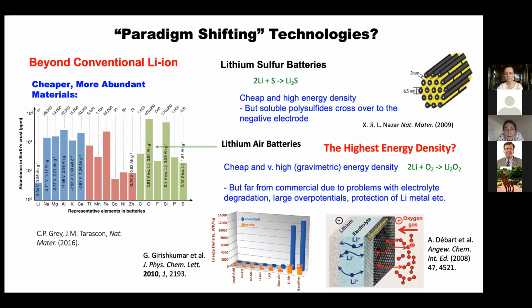If you really want to go cheaper, you should get rid of your transition metals, and maybe you can use sulfur and make a lithium sulfur battery, and you get very high energy densities because both lithium and sulfur are light, and of course sulfur is cheap. But you've got problems associated with the fact that the sulfur goes from S0 to S2- via polysulfides, and these polysulfides dissolve into the electrolyte and act as redox shuttles. And so that's the challenge in that field.